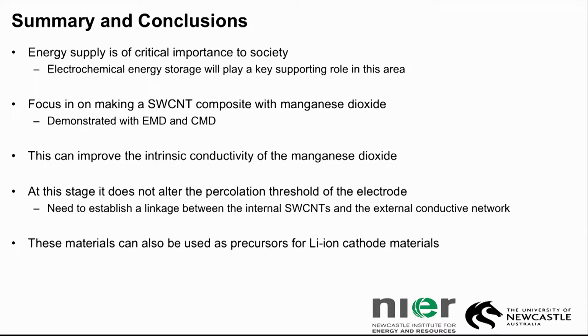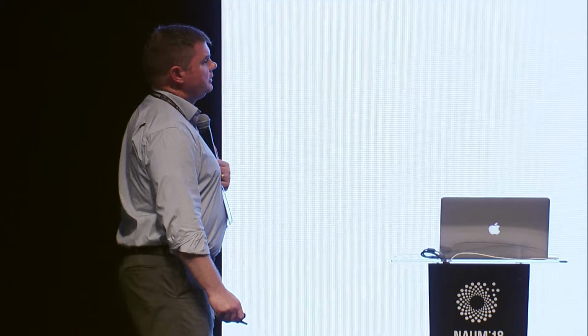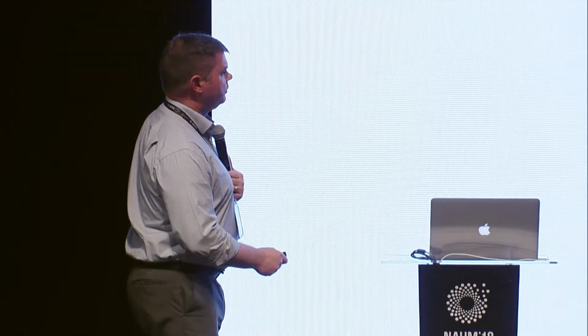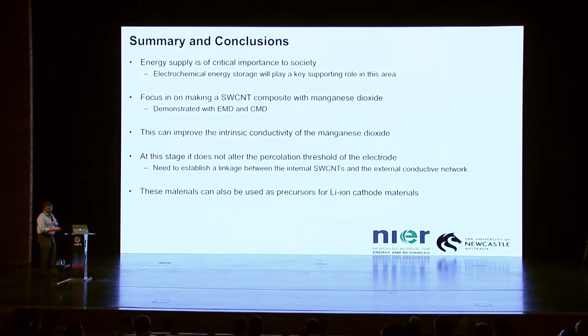One final note that I will make as well is that these materials can also be used as precursors for lithium-ion cathode materials. And so with the embedding of the carbon nanotubes into the manganese dioxide phase, we have the capacity to then transform them into lithium-ion materials, like lithium manganese oxide and a range of others, all the while still maintaining that carbon nanotube network within that path.